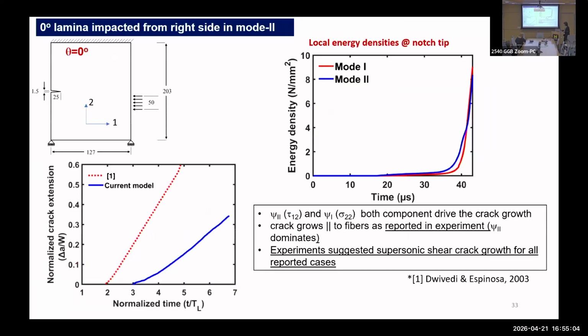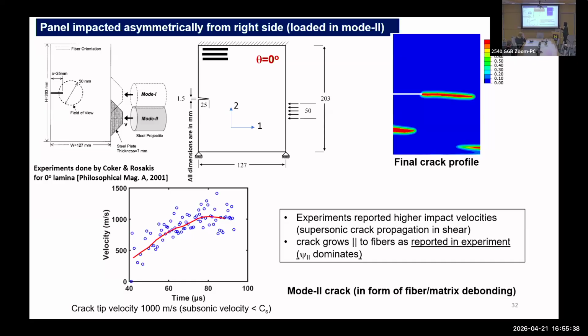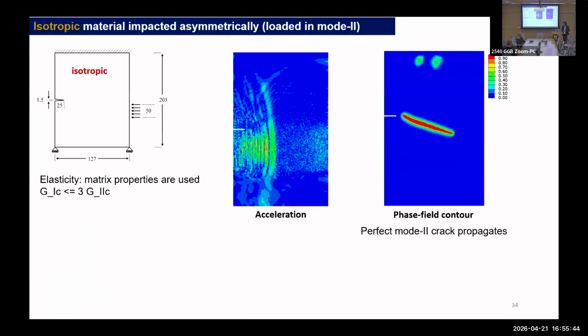And of course, there is modeling published in 2003, where they used an elastic plastic constitutive description for the lamina level. If you remember, our constitutive description is purely linear elastic, so there is no dissipation because of plasticity, which is probably another reason that we are seeing a little slower crack growth. We do not see why it should not work if we can probably constrain this part of the damage initiation. Probably we can get a better prediction. We have to work on that. I'm not claiming anything before doing that.